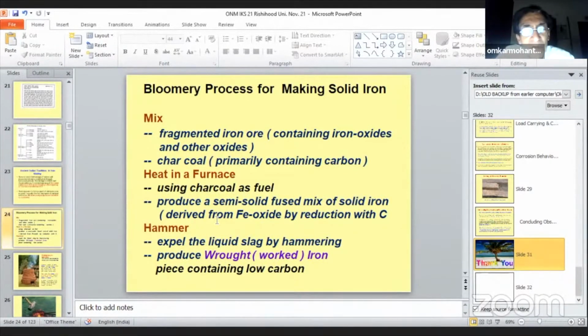Around 1150 to 1200 degrees centigrade, all these oxides melt, become liquid, and we call that this becomes a mix of solid and liquid. Why solid? I will pause for half a minute so that you will think. Why solid? Because we have just now discussed a minute back that the melting point of iron is very high. So when iron oxide is reduced by carbon, that means that carbon has taken away the oxygen, which means from the iron oxide, what has remained is pure iron.